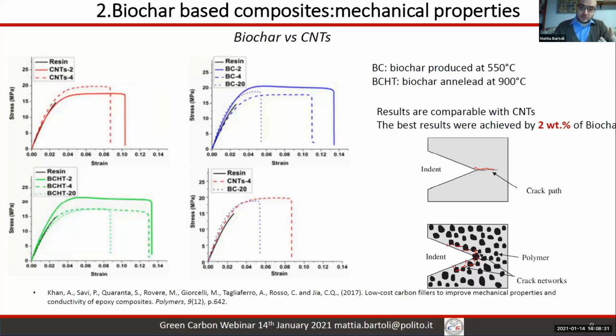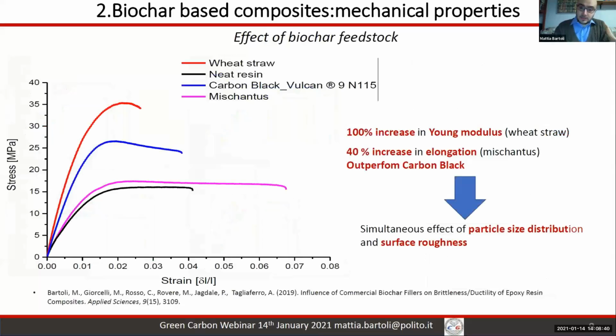At this point, a lot of questions arose. Firstly, if we change feedstock, we are able to change the properties of the composites. So we used different biochars using several kinds of feedstocks. Here you can see results regarding biochar used for enhancing mechanical properties of epoxy resin, produced from wheat straw and miscanthus. And as you can see, different biochars induce different properties. We found that this was due mainly to different things. The first one was related to the fact that different feedstocks lead to the production of different biochar with different grindability, and different grindability leads to different particle size distribution. Particle size distribution is the first parameter that affects the mechanical properties.